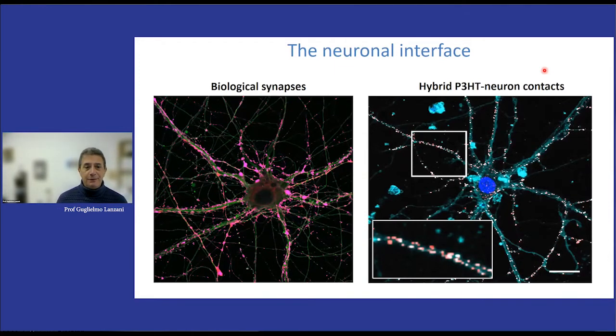The other thing that is, I think, very suggestive and interesting, is the comparison with the picture on the left. The picture on the left is an image, using a staining dye, but is a mean image of biological synapses. So these are the natural synapses of the neuron. And you see that the distribution of nanoparticle docking to the membrane on the right looks pretty much like the distribution of synapses on the left. So what we claim here is that our photovoltaic nanoparticles behave like or establish artificial synapses that stimulate the neuron. And there are hundreds of nanoparticles in a neuron.